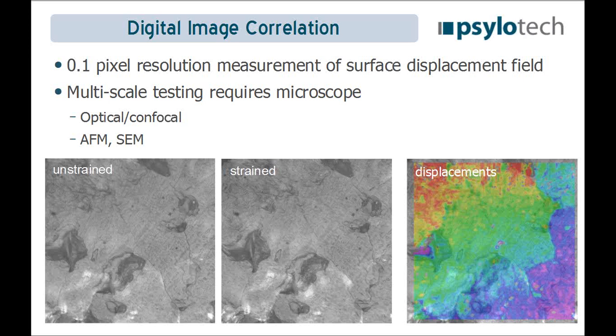And of course, if you have a displacement field, then you're able to calculate the strain field. So it's a non-contact method of being able to get the full 2D surface strain field on the surface of a specimen. So the instrument requires this digital image correlation to really be able to work on the multiple length scales. And of course, you need to be able to take pictures, so you need microscopy.